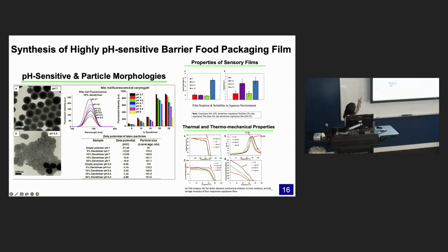At pH 7, you can see we got 100 nanometer particles, and after pH 5.4, you can see these little dots are the dye released out. This is showing different kinds of dendrimer as coating materials, what the particle size change is, and the fluorescence shows we can control the pH; at least 0.5, we can see the difference. So it's very sensitive, and the right-hand side is showing the thermomechanical properties and the hydrophobicity.